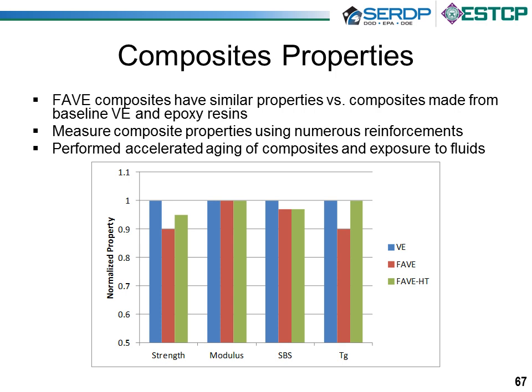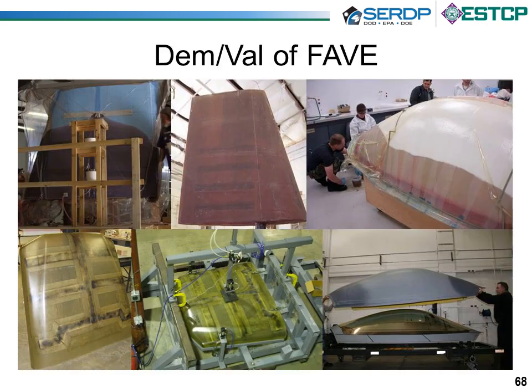Nonetheless, these resins perform very well when it came to demonstration and validation for various DoD applications, including in the top left, you can see this composite rudder that we manufactured, that had excellent performance and met all the requirements necessary for a composite rudder. The bottom left, we could see this truck hood that we manufactured and then tested using that test rig shown in the middle picture. Basically, we can load the hood with various weights, fatigue it, apply torsion, and the composite performed similarly, essentially no different from that of the commercial vinyl ester resin used.